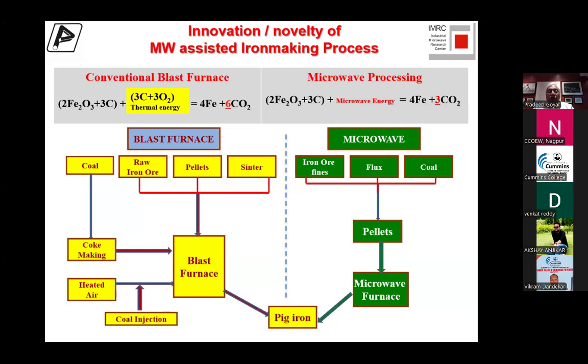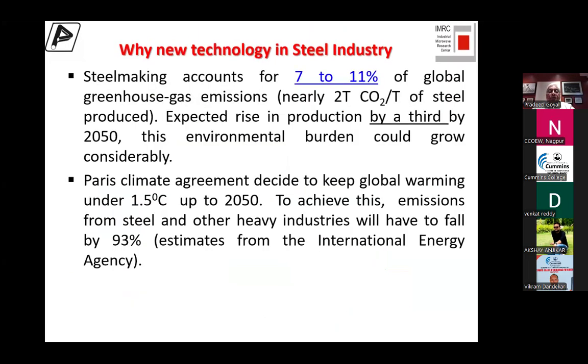And look at the clean process that we have. We have iron ore fines, we have flux, we have coal fines, we make pellets, and we directly reduce it in a microwave furnace to produce pig iron. While in the other process, you have to take the coal, make it into coke, you have to have coal injection into the blast furnace, you have raw iron ore, you have pellets, you have sinters, put it in the blast furnace, and then you make pig iron. So there's a huge reduction in the number of steps in making pig iron by this process.